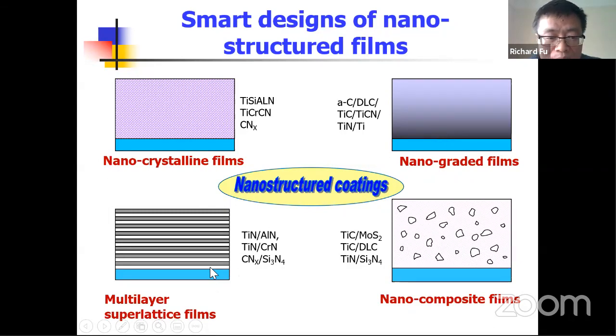Or we can use multi-layer nano-layer designs, so the crack would not easily propagate through it, which increases the energy and increases toughness. So this is another design. And also we can use the nanocomposite coating design, where we embed nanoparticles within a matrix of a tough substrate. Then we can achieve very good performance.